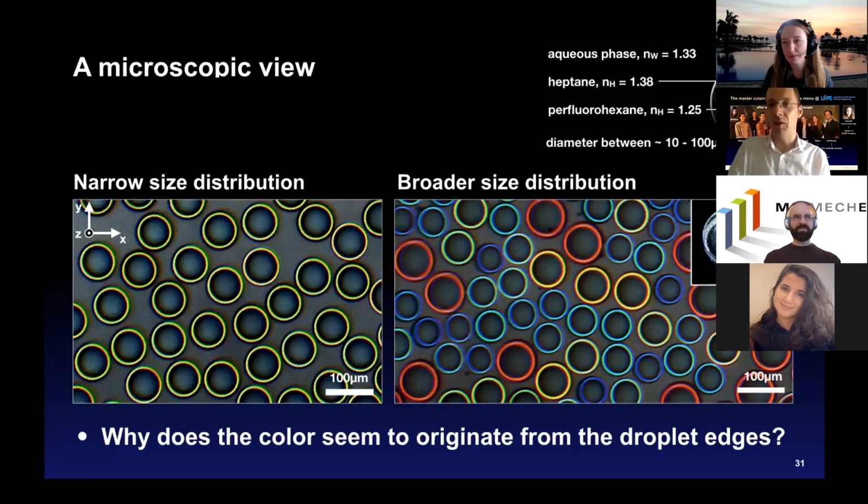There's one phase, this is often a heptane or a hexane, and this could be perfluorohexane. There's two different types of surfactants, and by changing the ratio, we can change these conformations. But you have to get the surfactant there. So that would define the speed of switching. What you also can do is you can put a surfactant in there that is light responsive. And so when that switches its conformation and changes the surfactant strengths, then it's the switching of that surfactant that defines the speed. And that can be in a couple of microseconds.